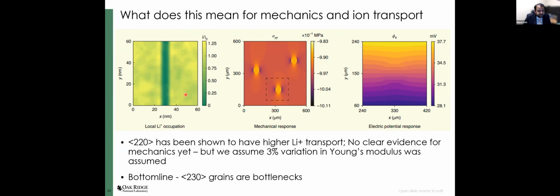And so on the left, you see essentially a lithium occupation image. So we have a 60 nanometer by 60 nanometer domain with a thin layer in between that is of a distinct phase. So we are assuming that the two outer rectangles are 220 and the middle lane is the 230 phase. If you let the simulation run long enough, what we find is that lithium essentially gets excluded from this domain, and we only have lithium occupying the higher conductivity domains.